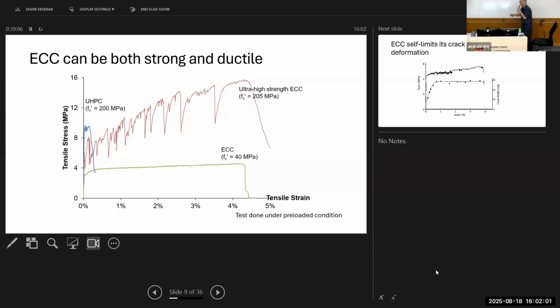Okay, so just now I showed you an illustrative tensile stress strain curve comparing those 3 materials. These 2 are real test curves. This is a common normal ECC with a compressive strength of 40 megapascal, not particularly high, but showing the very large strain capacity, over 4% strain, before it finally fails. The blue line here shows a UHPC, which is famous for its high compressive strength, over 200 megapascal. And it does have some tensile capacity after its initial cracks, although typically the strain capacity is less than 0.2%. So it's limited ductility, very high compressive strength.